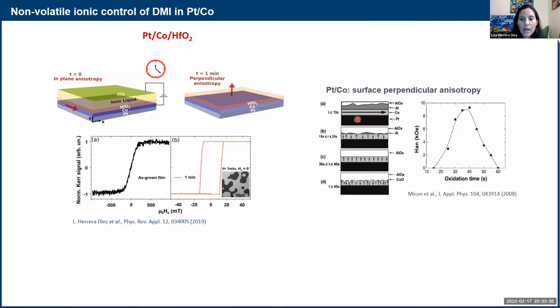So we know very well from previous studies where they did oxidation on purpose that the anisotropy can be in plane when it's under oxidized. And then if you keep oxidizing it, at some point you will get PMA because it will be optimally oxidized. But then if you overdo it, if you keep putting oxygen inside, then you're going to go back in plane.